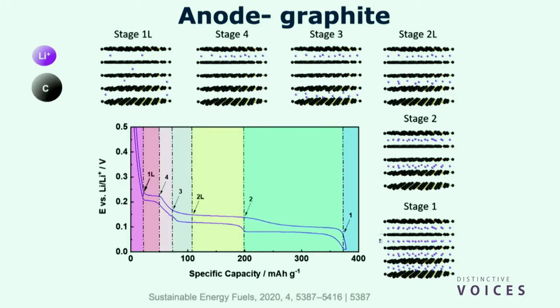Okay, so what happens at the atomic scale when we put lithium into an anode and take it out? If one were to do electrochemical measurements in a laboratory to see what the voltage of the anode is versus lithium metal, and correlate that to what's happening physically inside the graphite particles, one would see, so black atoms are carbon, the purple atoms are lithium, you look at the voltage versus how much lithium goes into and out of the graphite. And you can see that when lithium goes in between these layers at the higher voltages, there are just a few lithium atoms between the layers. But as we start to put more and more lithium, it goes in certain steps.